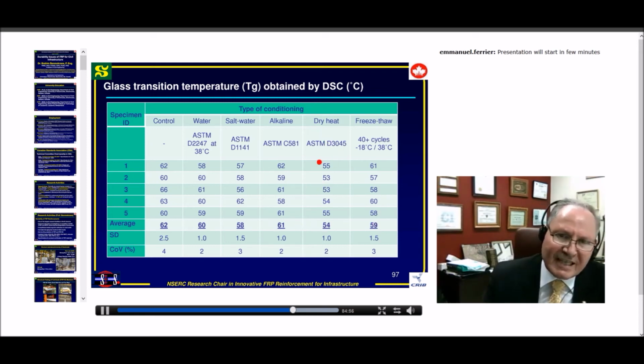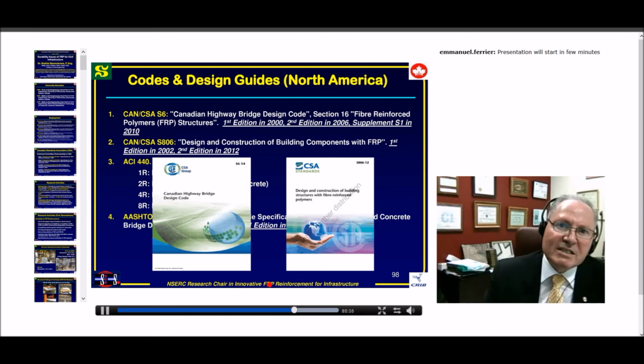What we found, dry heat, we found it really the most critical from this testing, for both mechanical properties and also glass transition temperature. For the DSC, be very careful, because in the standard we are specifying a number with DSC, but we also have a number with the DMA. And with DMA, you have 3 approaches to determine the Tg. If you are looking at chemical degradation, physical degradation, or mechanical degradation, you have different kinds, but there is one kind which is close to the Tg. So be careful about that.